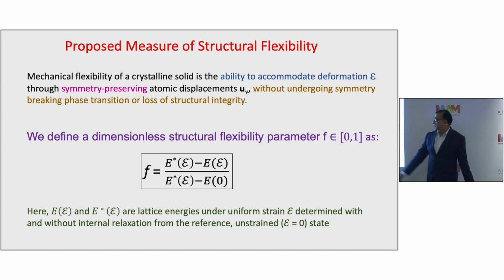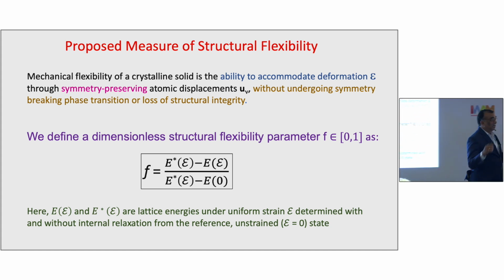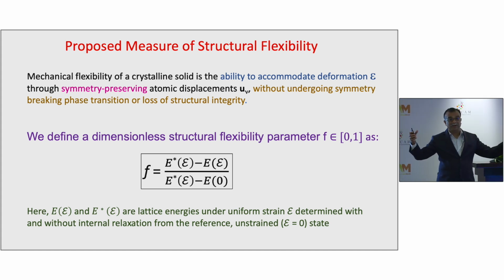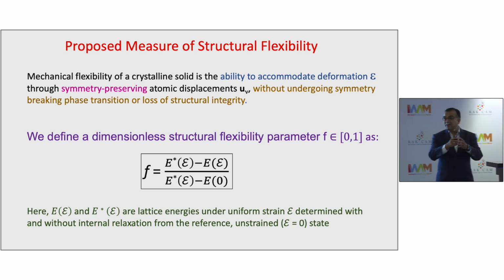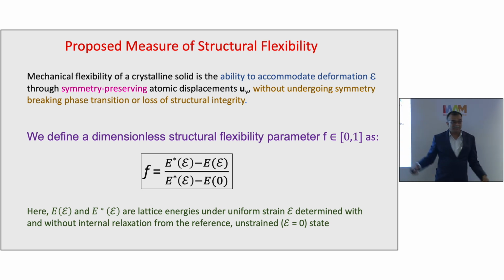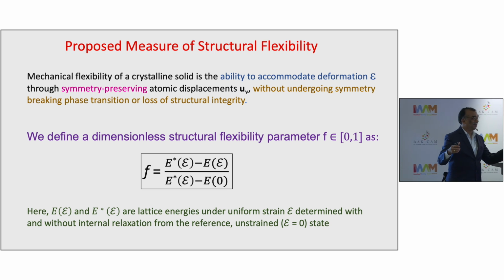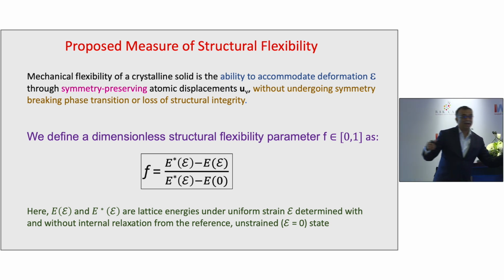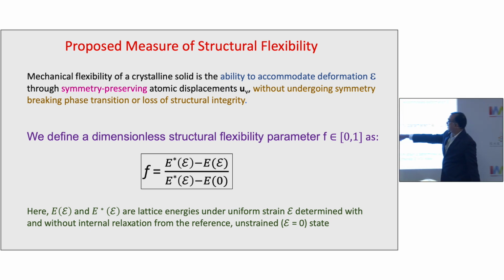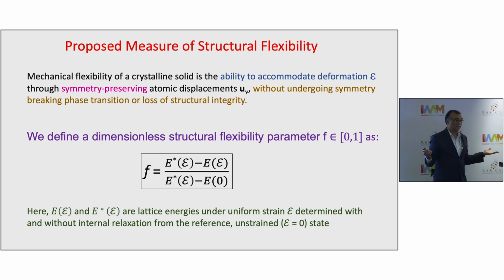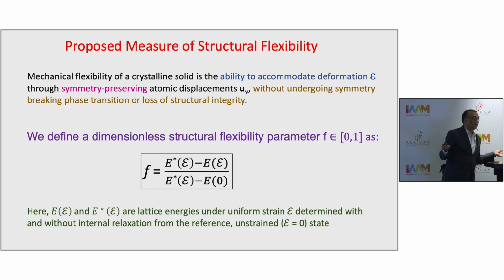The denominator is the energy cost of uniformly deforming a crystal without letting it adjust internally. So imagine you applied stress at a very infinitely fast pace. The crystal will deform instantaneously, and that's the cost in the denominator. The numerator is when you allow that crystal to relax for a given applied mechanical stress, and it lowers that energy. So the fractional reduction in the elastic strain energy by internal structural relaxation is flexibility in our notion. So it's linked with energy scales rather than length scales and deformation.